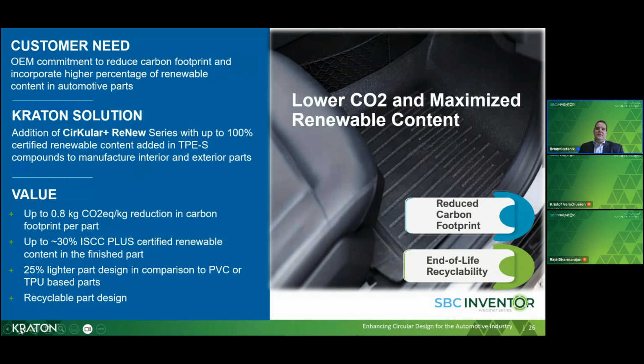So as an example, just dropping in Renew, the equivalent of our traditional polymer, netted the customer a 0.8 kg CO2 equivalent per kg reduction in carbon footprint per part. And so the finished part had about 30% renewable content, plus the part was 25% lighter. But I think the best benefit is that having replaced a PVC or TPU with TPES means that the part is now fully recyclable.